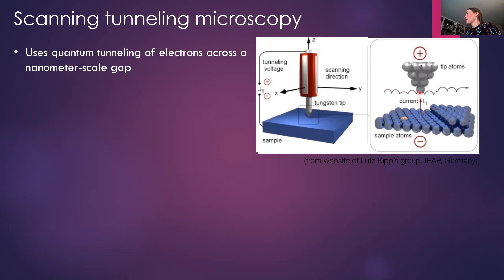And then you get some tunneling current. Now, if you imagine you get this tunneling current, it's some value here. But if you move the tip over a little bit, so that the tip of the atom is like between the atoms on the sample surface, your tunnel current is going to go down. Because now you've increased the gap between the tip and the sample. So in that way, the tip is very, very sensitive to changes in height on the surface. So you can see this trace here, it is following the blue atoms. And then here, you can see that it actually goes up again, because there's an extra layer of atoms here. So this is the measurement of an atomic step.